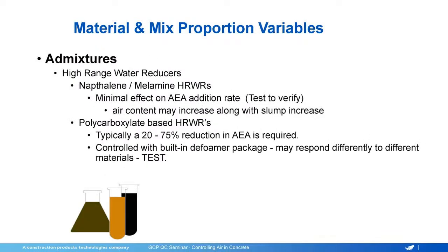High range water reducers, not a lot of naphthalines and melamines around anymore. They don't impact it too much unless you get the concrete too fluid, and then you're not going to be able to keep the air in there. Polycarboxylate based high range water reducers all have defoamers in them. They're all different. Typically, you will need less air entrainment when you're using a polycarboxylate admixture, which is probably 99% of the high range water reducers on the market today.